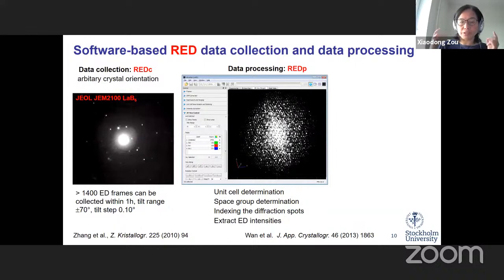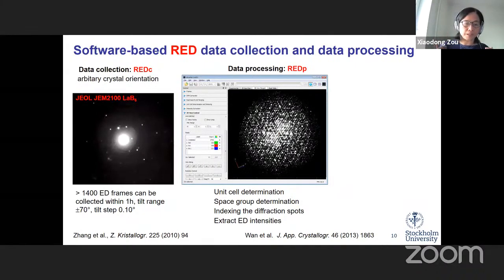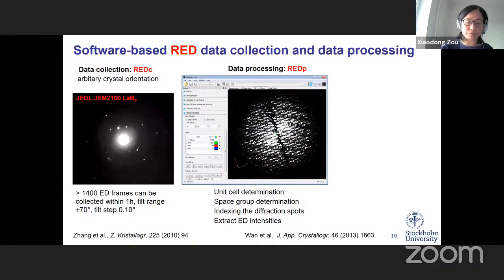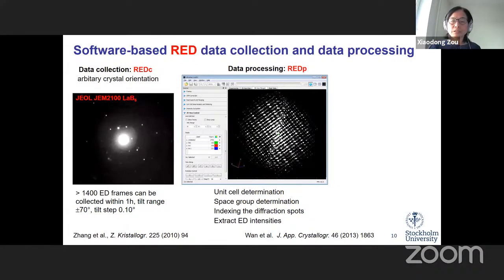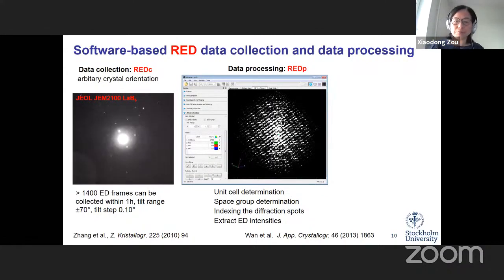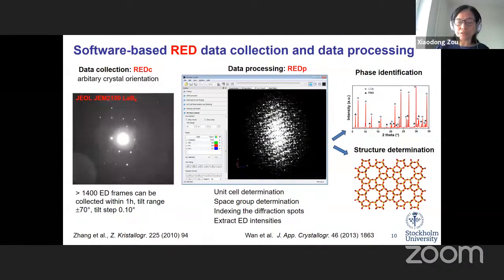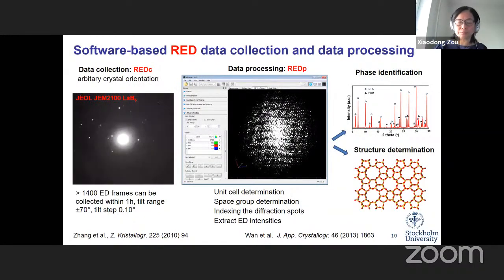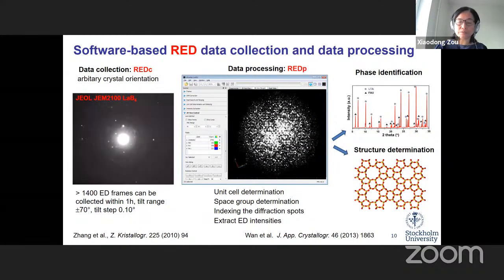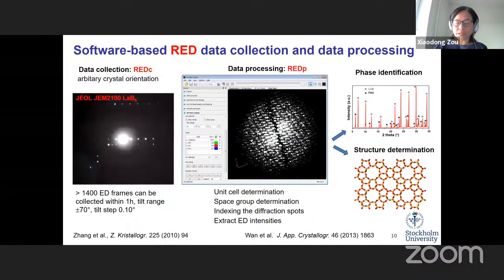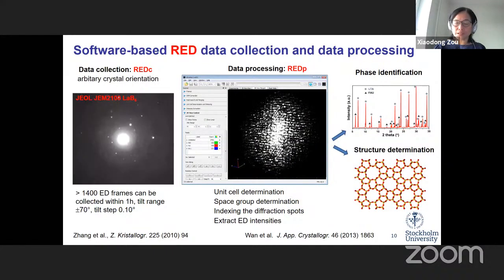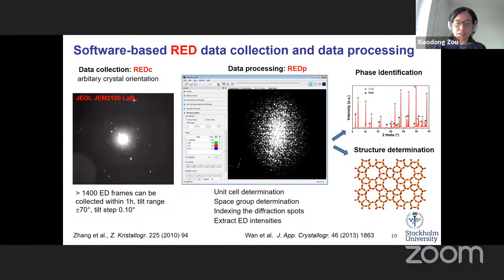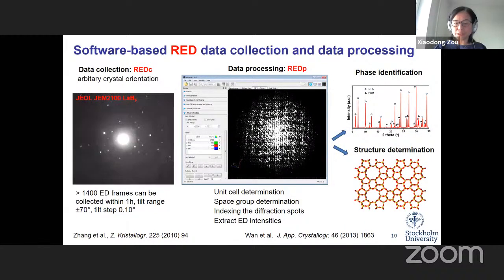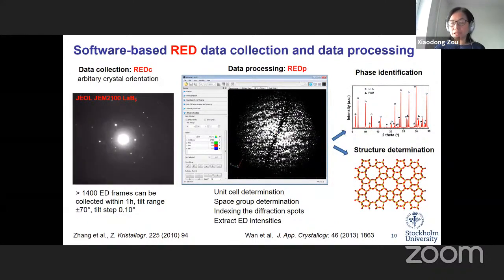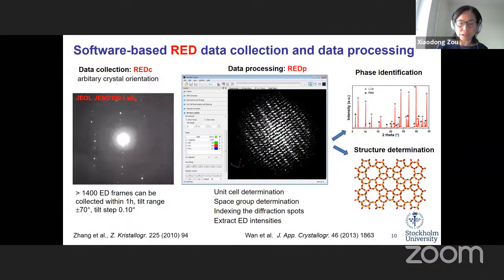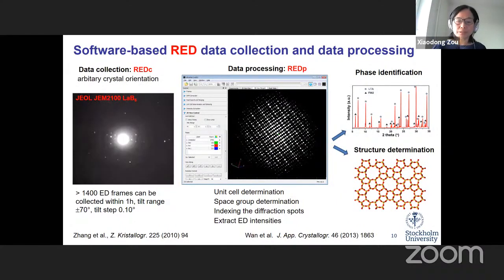Using this, we can determine the unit cell parameters and the space group, and also get the intensities from these diffraction spots. With this information, you can make phase identification, because from the unit cell and space group, you know which phase your crystal probably corresponds to. And if it is an unknown phase, you can use the intensities extracted from the diffraction patterns, together with the unit cell parameters, to determine the crystal structure in the same way as for single crystal X-ray diffraction. It is a well developed technique.